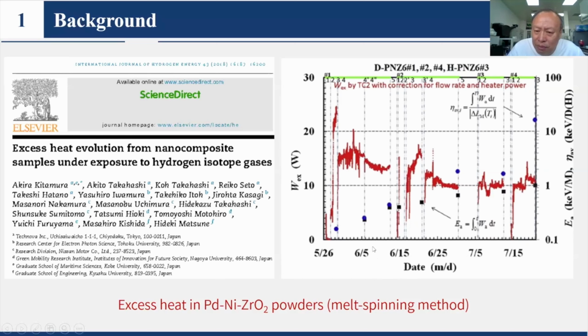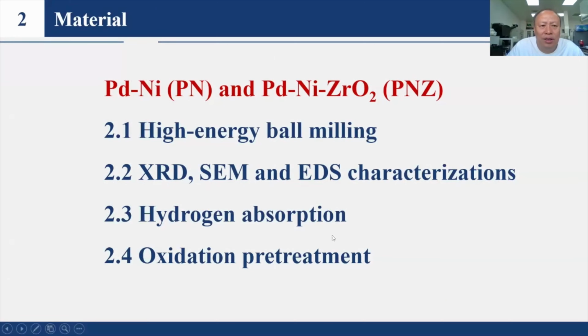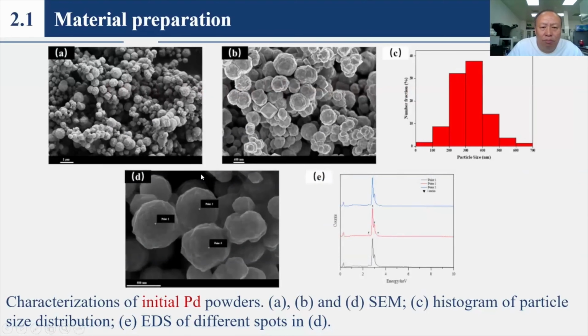They made the samples using the melt-spinning method. Now we also use palladium-nickel powders and palladium-nickel-zirconia powders, but we use a different manufacturing method: ball milling. This is the initial palladium powder. We can see the average particle size is around 300 nanometers, and this is an SEM picture of the palladium.